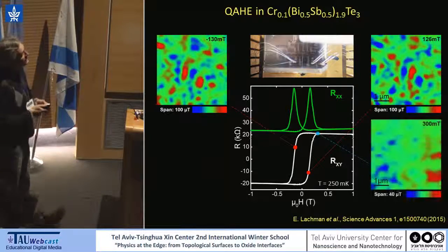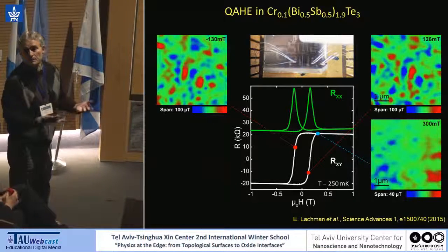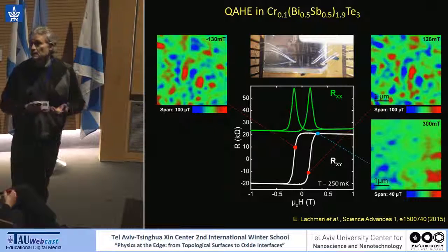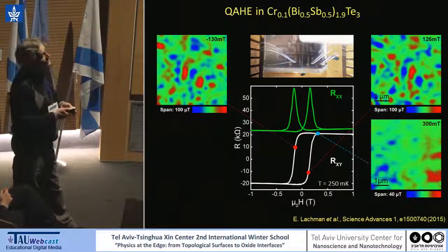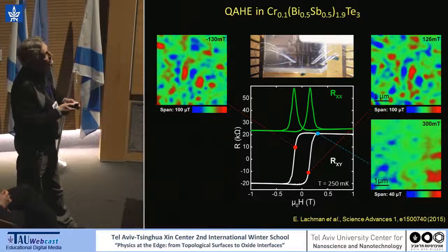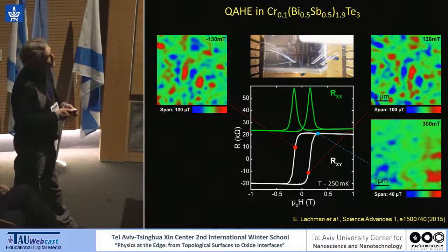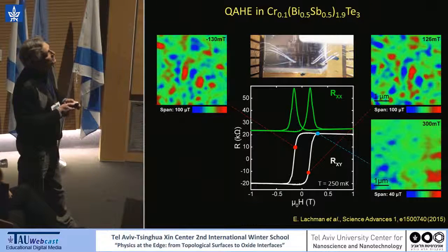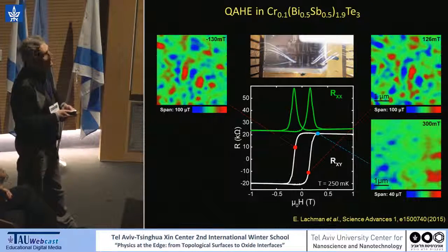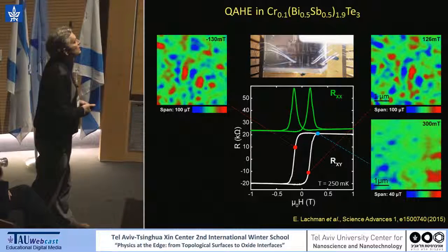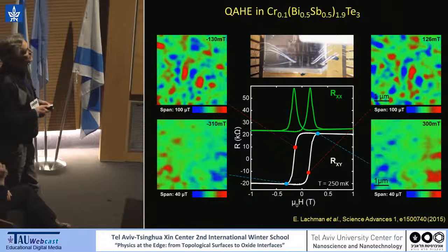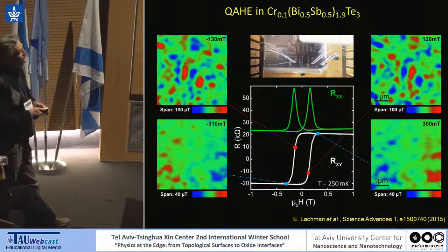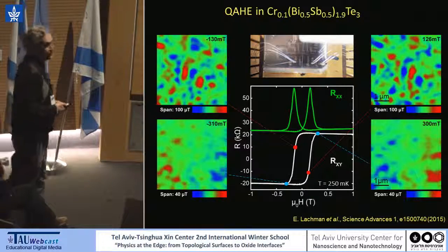But now we look at the fully magnetized state, which we expect to be a long-range ferromagnetic state, uniform, in which case we would see nothing. But you see that actually it is highly inhomogeneous, quite similar to this. It's about half the signal, but still very far from long-range ferromagnetic order, as we would expect. If we go to the opposite point, we see a very similar picture. And again, it's essentially the same, just with the colors inverted. Blue here, red here, and the opposite.